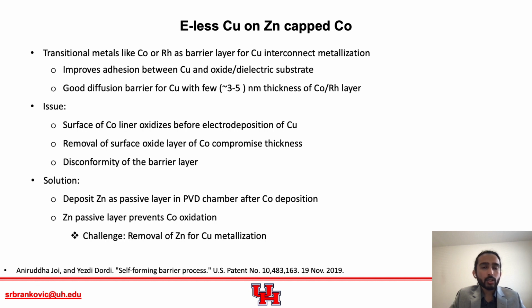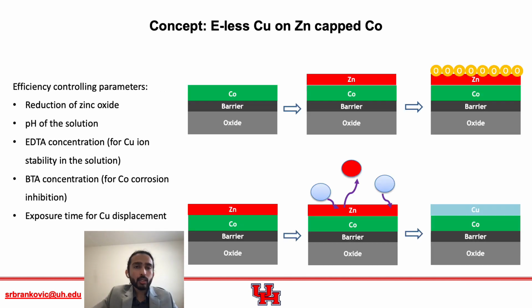So one of the solutions for this problem, as proposed by Joy from Lam Research in a previous publication and patent shown here, is that they deposit a zinc layer in the PVD chamber right after cobalt deposition. So this zinc layer serves as a passive layer and it prevents oxidation of cobalt. But there is another challenge now, that we need to remove this zinc for copper metallization. So the aim of this project is to deposit a very thin copper layer on top of this cobalt with removal of zinc so that this copper layer can serve as a seed layer for further electroplating.